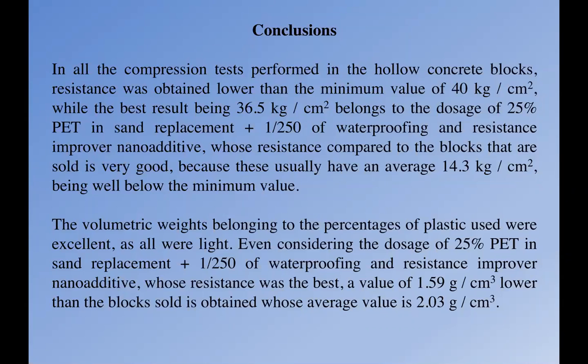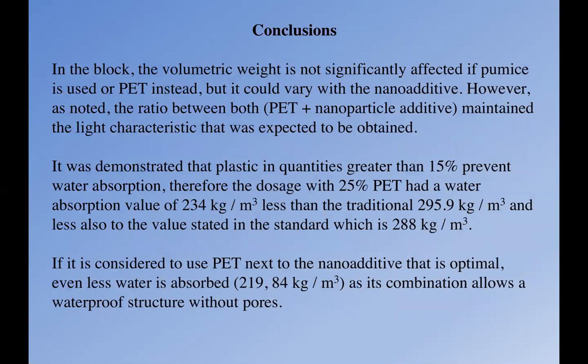The volumetric weights belonging to the percentage of plastic used were excellent, as all were light. So here are a few more conclusions: the volumetric weight is not significantly affected if PET is used instead of pumice. It was also demonstrated that plastic quantities greater than 15% prevent water absorption, and it is considered that using PET next to another optimal material, even less water is absorbed, as the combination allows a waterproof structure without pores.